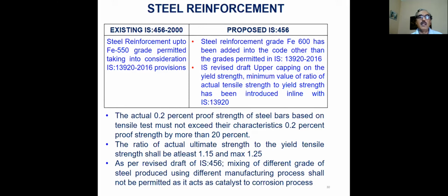Steel reinforcement up to Fe-550 grade was permitted, taking into consideration the 13920:2016 provisions. Now in this code, steel reinforcement up to 600 has been permitted, as was told by Prof Murty also. We are keeping an upper capping on the yield strength. A minimum value ratio of actual tensile strength to yield strength has been introduced in line with 13920 - earlier we had it in 13920 but not in 456. So we have put that the actual 0.2% proof stress of steel bars based on tensile stress must not exceed the characteristic value of 0.2% proof by more than 20%.